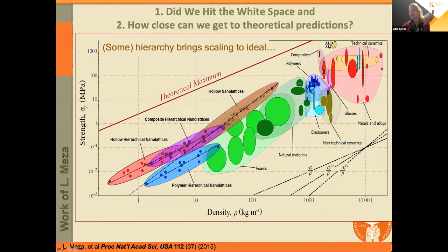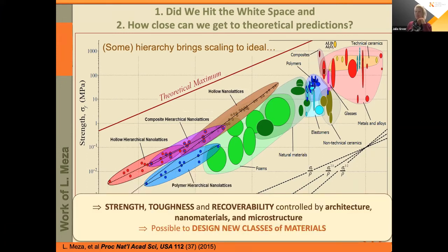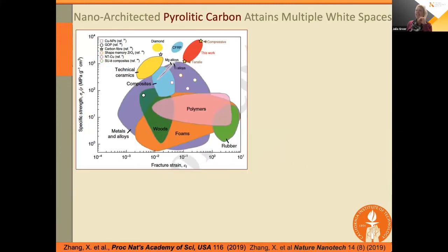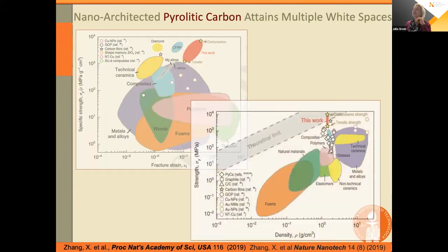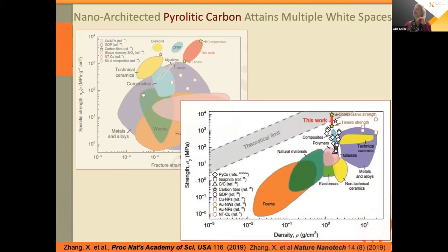Now, these are the hollow nanolattices from the alumina work that you saw earlier. These are the fractal nanolattices. And what you can see is that, sure, we're not quite in the white space where we would like to be eventually, but it's definitely paving a way to venture into that. So this combination of the nano-size effect and the nano-architected materials certainly offers this pathway to get into the white space. Now, what we also learned is that when you're dealing with carbon materials, we can, in fact, get very close to the theoretical limit, and especially at the higher densities.